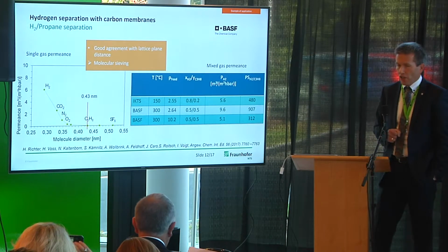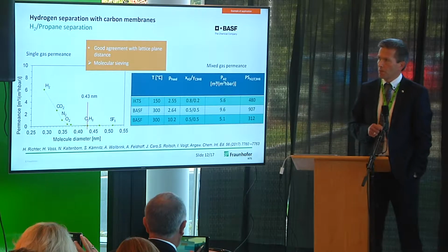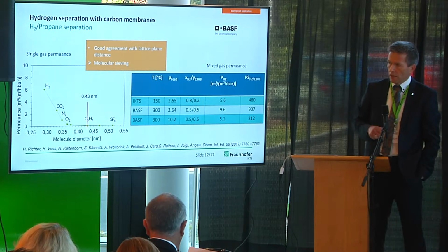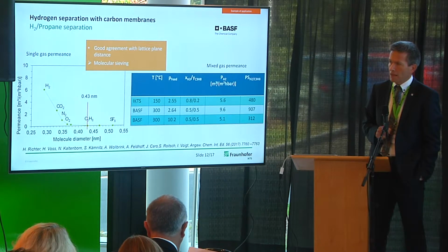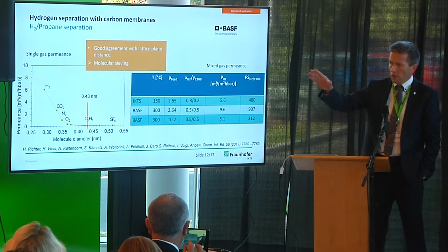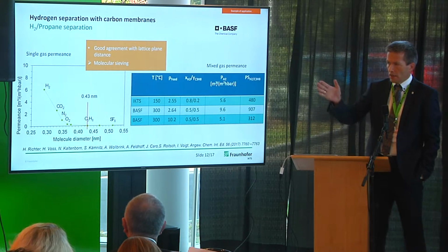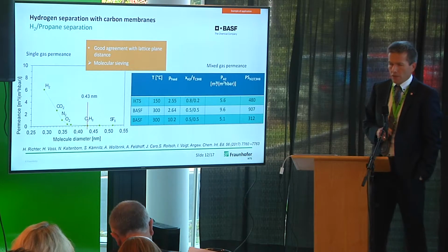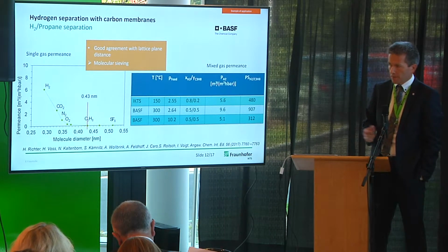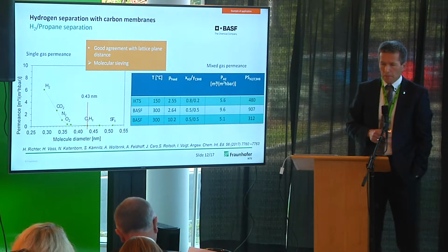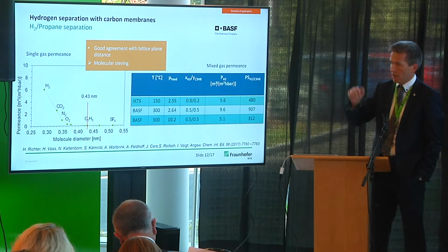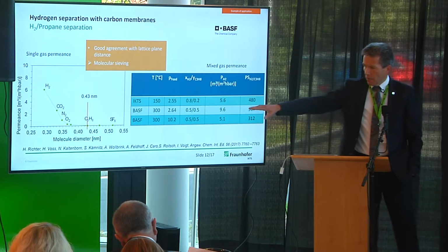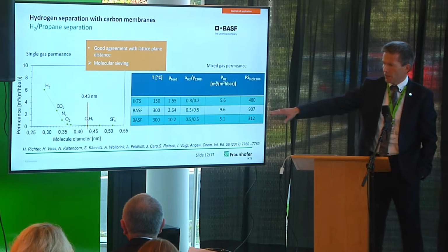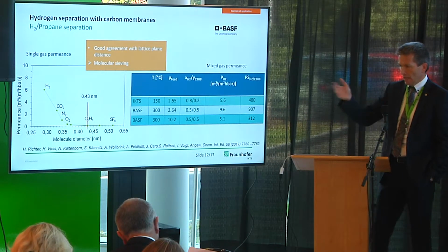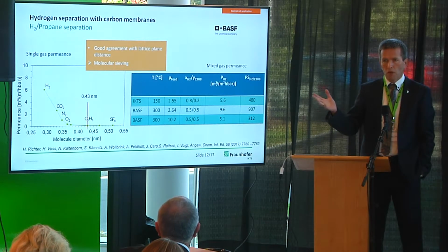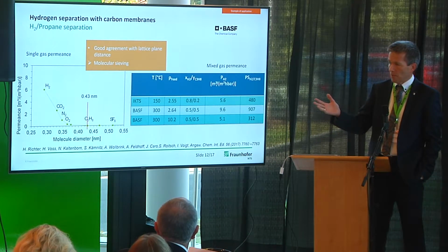Well, next example is gas separation with carbon membranes. This was a project together with BASF. Here we showed the single gas permeance of the carbon membranes. We found that we have a very good permeance for hydrogen, and the hydrocarbons C3, C4 are completely rejected. This was the basis for mixed gas measurements and tests together with BASF. And you see that the high hydrogen permeance, high perm selectivity was confirmed also in mixed gas separation. And this confirms that we have here a molecular sieve behavior and a very stable performance of the membrane.